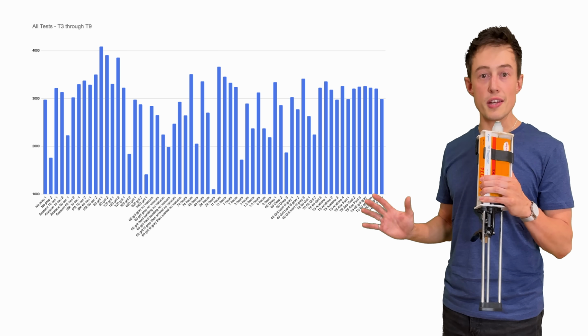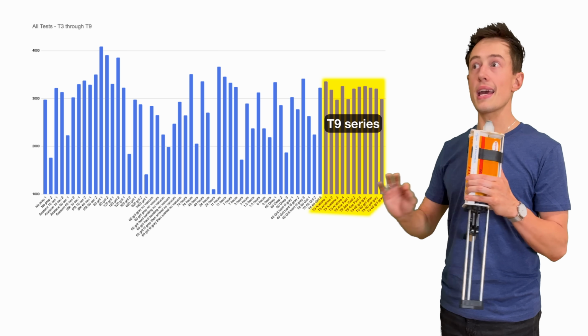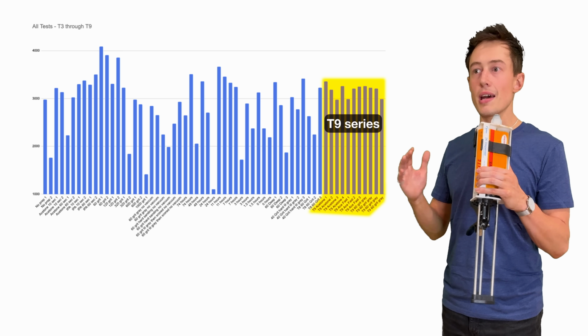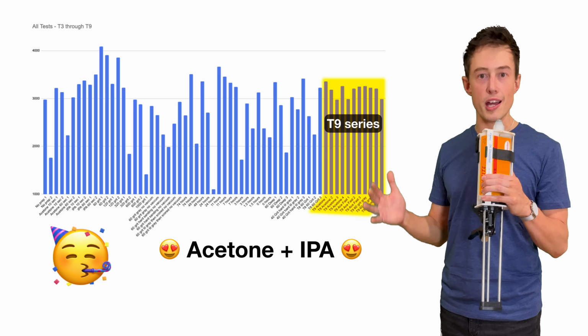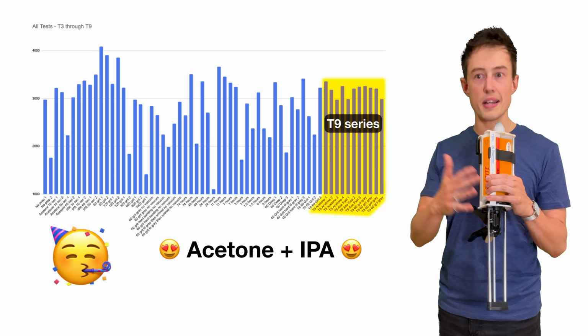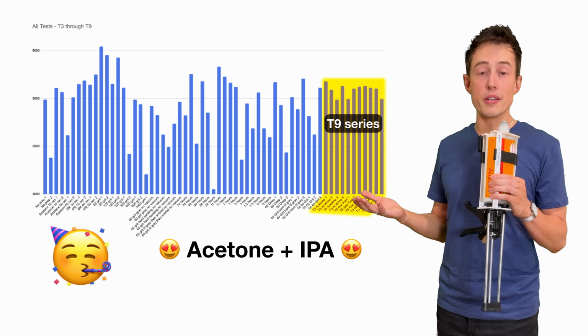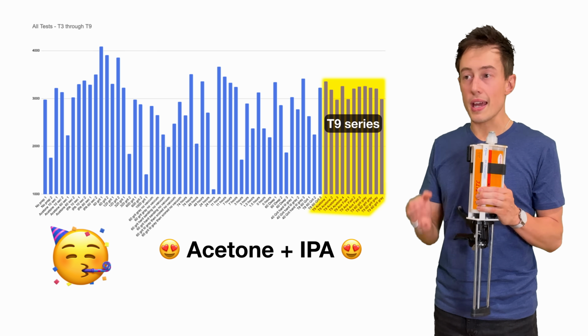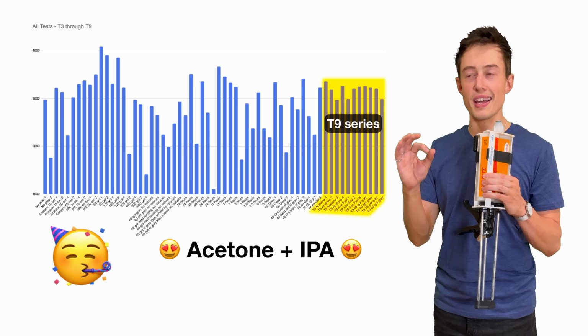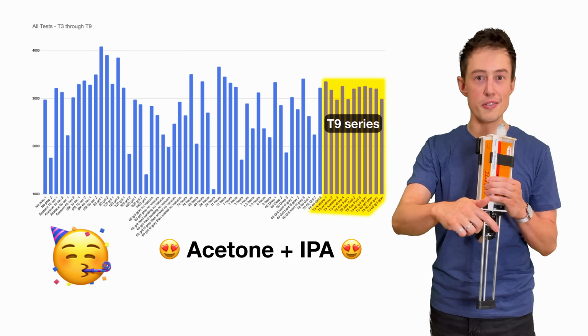The standard deviation of these coupons was lower than any other test series I ran, and that means it worked. Acetone and IPA achieved the consistency that the tech claimed it would. It seems like this is really the trick to getting repeatable bond strength, and it is remarkable how close I came to figuring this out during the earlier series of tests.